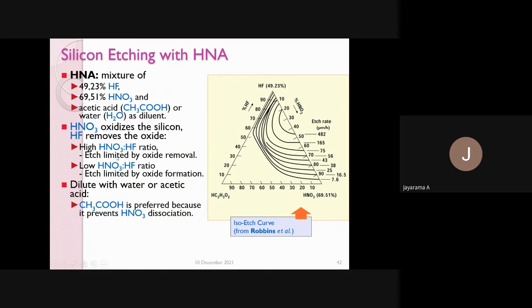The etch rate is limited by oxide removal with a high HNO3 to HF ratio. With a low HNO3 to HF ratio, the etch rate is limited by oxide formation. So if you change the ratio, the etching rate will become different. Diluting with water or acetic acid is preferred because it prevents HNO3 dissociation.